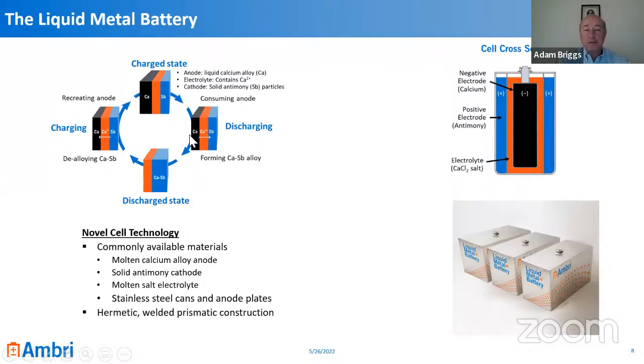So this battery system can be driven completely through to its complete reaction. So therefore, all of the calcium can be utilized. And then upon charging, the calcium 2 plus goes back across the electrolyte, forms elemental metal calcium on the anode collector, and again can be driven all the way to the full calcium is back in its spot on the negative current collector. So it means that a battery can go from 0% to 100% to 0% without any concern for the health of the battery or any safety related issues.